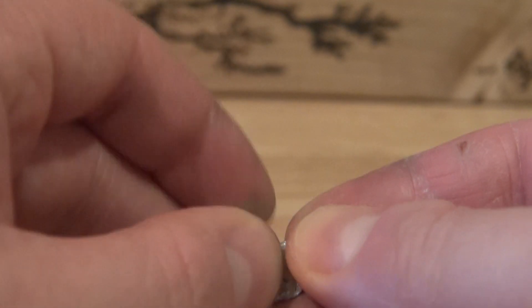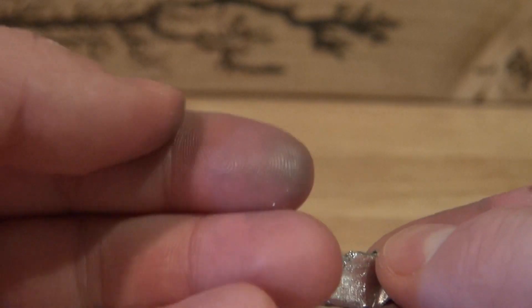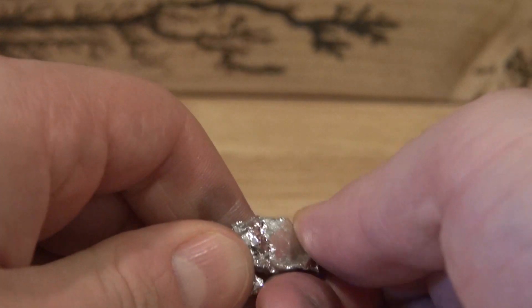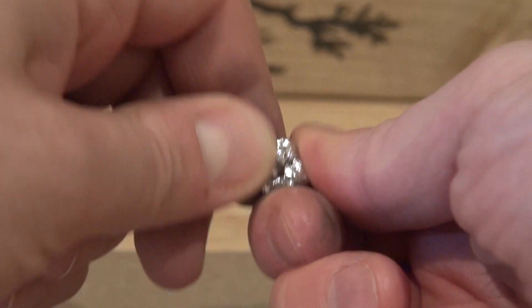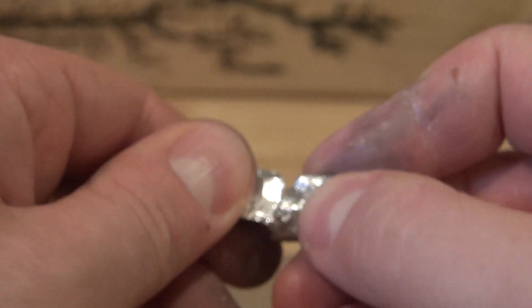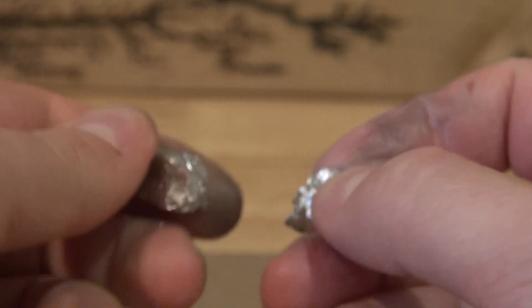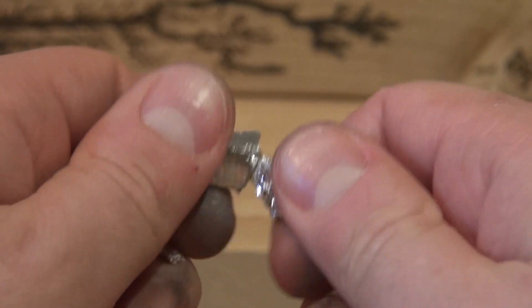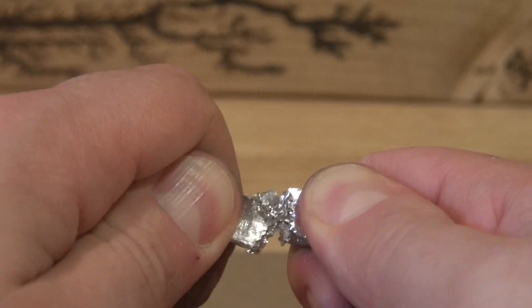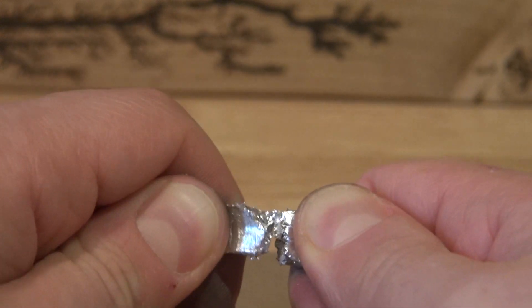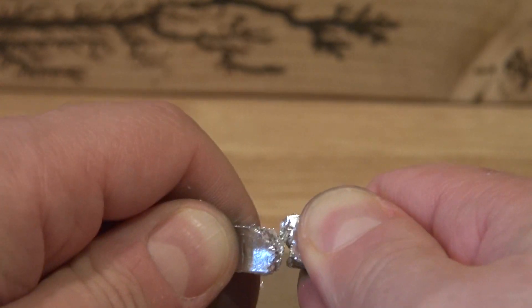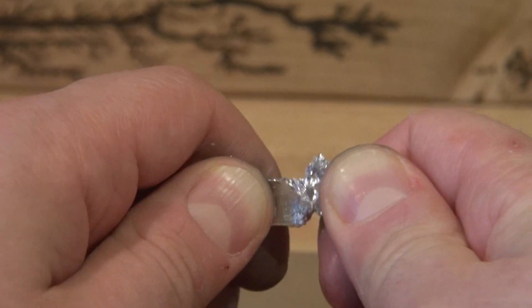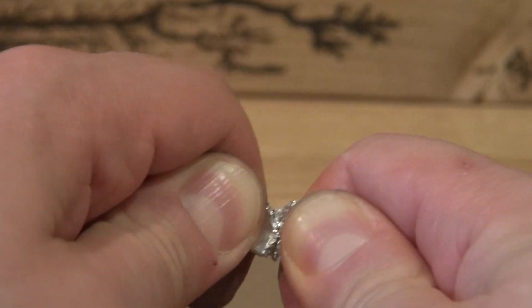Now, this piece of indium that has been contaminated by gallium loses all of its original properties. As you can see, it's more brittle. I can break it apart with my finger. It won't deform, it'll just break. And cold welding is impossible. It will not cold weld because the crystalline structure has changed, which then, as you can see, rubbing it together will cause it to break instead of cold weld.